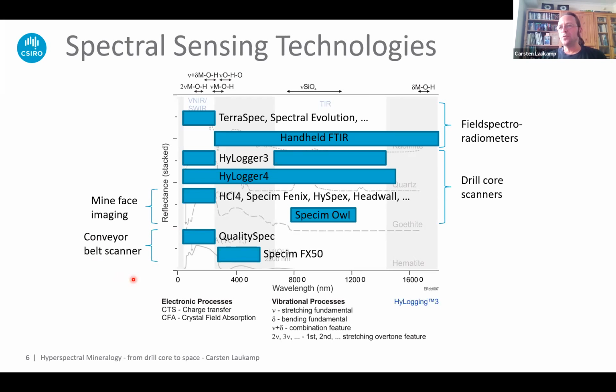Since maybe a few years, 3-4 years now, companies are more and more playing around also with conveyor belt scanners. So there are some instruments like the QualitySpec or SPECIM's FX50 that are basically attached to conveyor belts in a mine, and they scan what's traveling on the conveyor belt underneath and try to identify, like BHP iron ore, for example, is using the system to identify kaolin content, iron oxide type, and moisture content. Because these 3 parameters are very important for them to understand if they can process the ore or not. Because if it's too wet, if there's too much moisture, then it clogs up the processing plant and they can shut down the mill for a day, which costs them several million dollars.